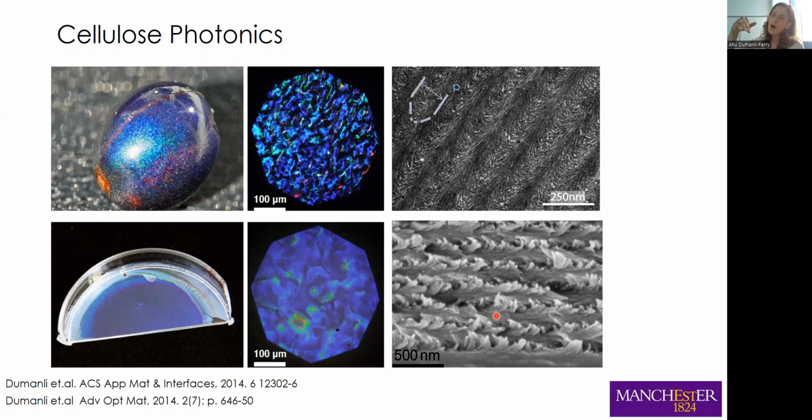As you go to thicker films, the merger of the tactoids and the formation of the cholesteric layers is getting a little bit messier, with more disorganization, more defects, and more multi-domains forming, and it is hard to predict from the pitch what the reflection color of the film overall is, because you have so many more domains. But when you have fewer domains and fewer defects in the films, the color is quite digitized, which was very nice to see at that time.